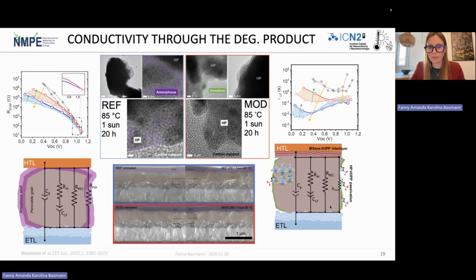So what we suggest is that, well, in the reference we have this core shell structure where grains are getting sort of dissolved into this new phase, and that this new phase has a lower resistance, provoking the changes that we see on impedance spectra.